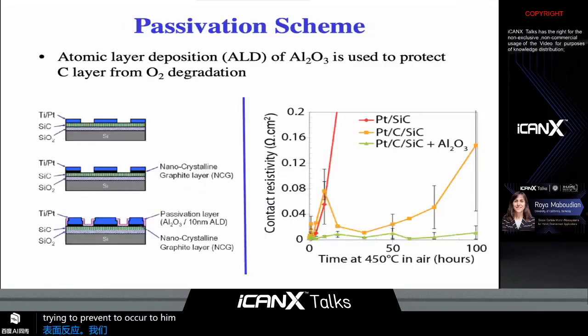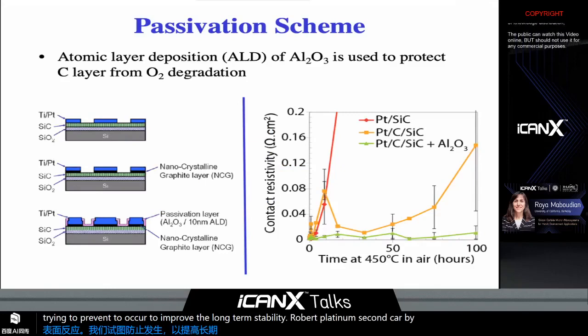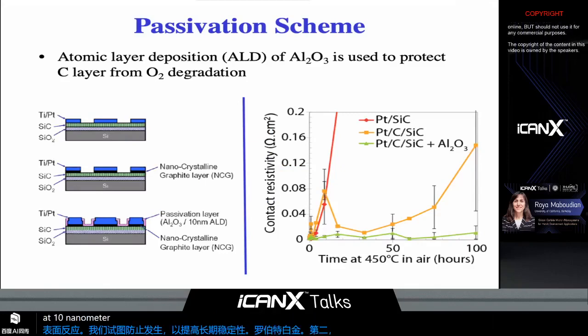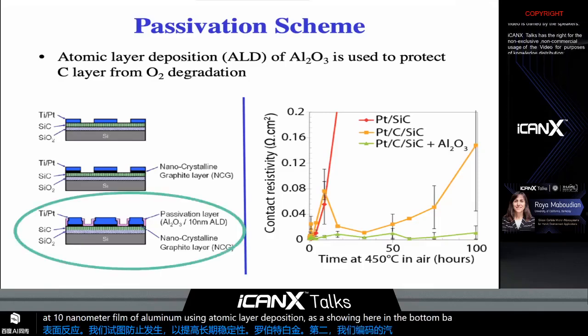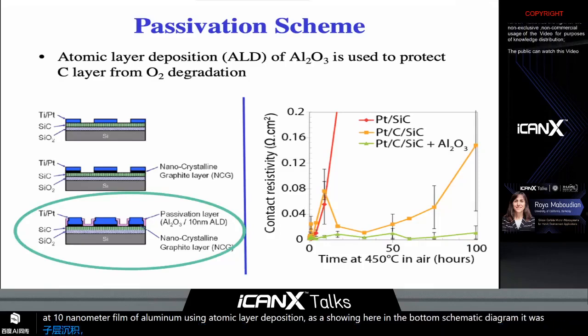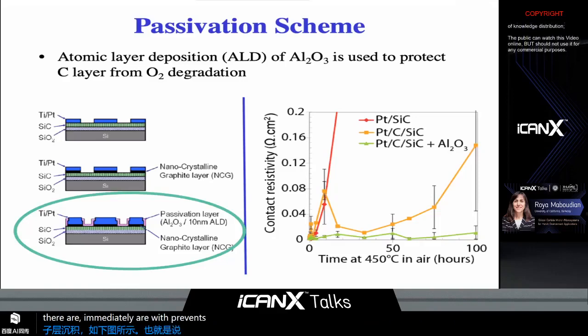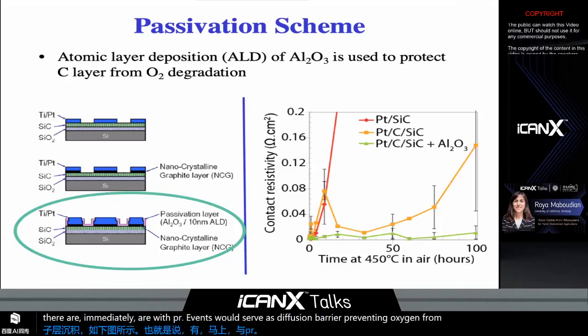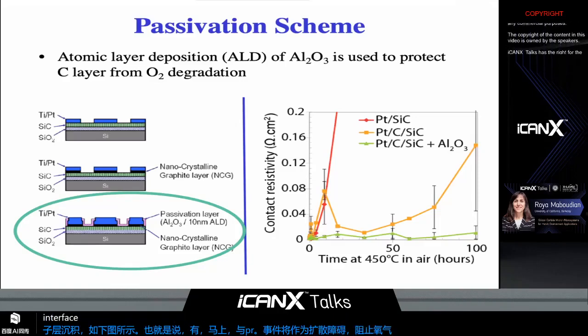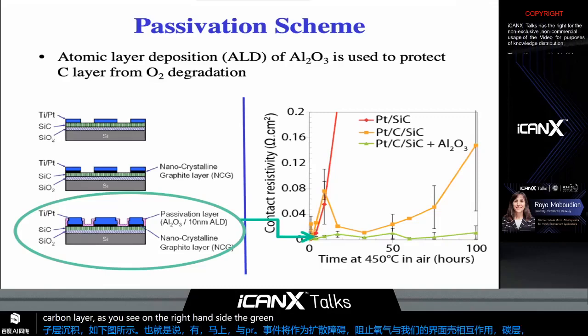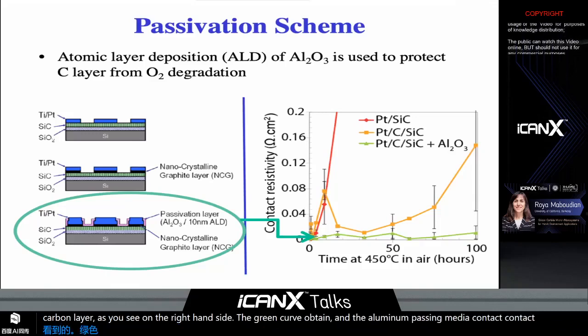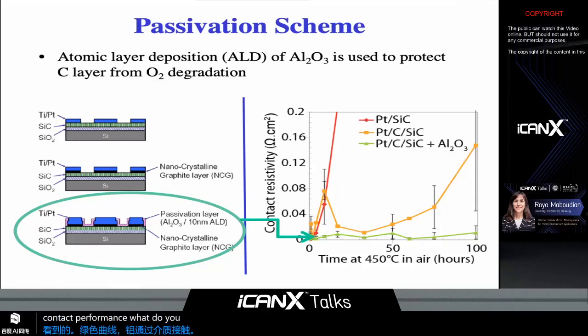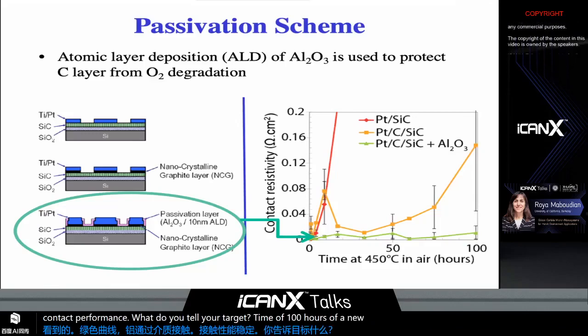To improve the long-term stability of our platinum silicon carbide contact, we coated the samples with a very thin, 10 nanometer film of alumina using atomic layer deposition, as shown here in the bottom schematic diagram. The aim was that the alumina layer would serve as a diffusion barrier, preventing oxygen from interacting with our interfacial carbon layer. And as you see on the right-hand side, the green curve obtained on the alumina passivated contact shows a stable contact performance for the entire target time of 100 hours of annealing at 450 degrees C in air.